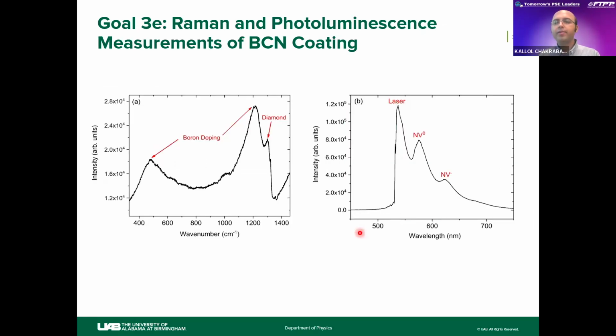Next, we did Raman spectroscopy to see how boron is bonded to carbon. Our diamond peak is shifted toward lower wave number, which suggests that the phonon is softened and we have some boron doping in our lattice. This is the typical spectra for boron doping, with peaks around 450 and 1200, confirming our synthesized coating is boron-doped.